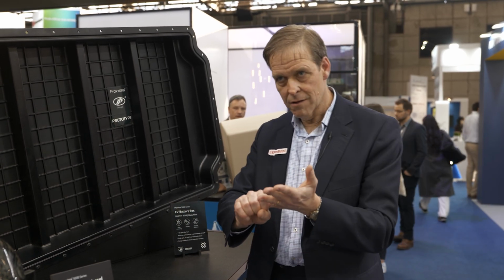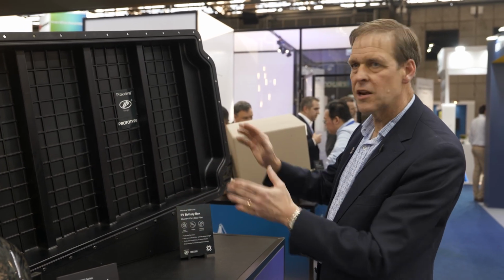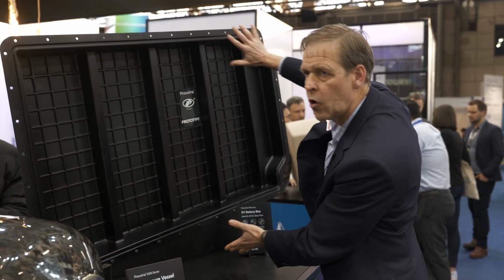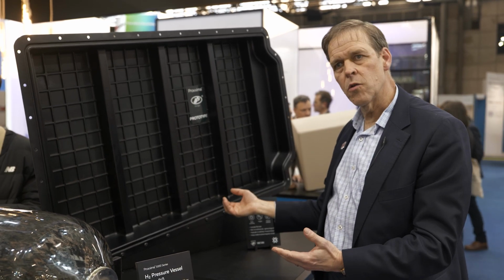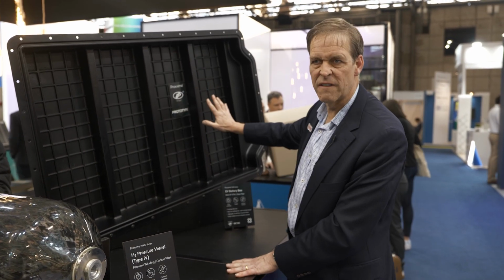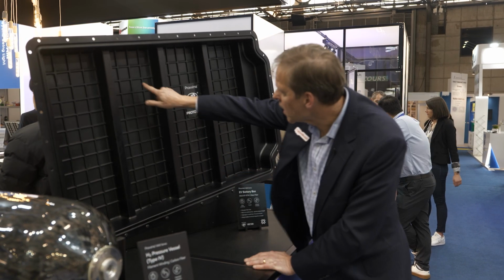So the first part is the viscosity that enables the cycle time, but also the viscosity that enables the design. So let's look at this design, and it is a prototype. We're moving now with Fraunhofer into a full production example of this. But this is 4-ply glass fiber, pre-formed through the shell here. But then what we've done is we've infused the Proxxima through a single gate, because it's such a low viscosity we don't need to double gate it. And we filled this mold in 15 seconds. So very, very fast. But the things that we can do are these.